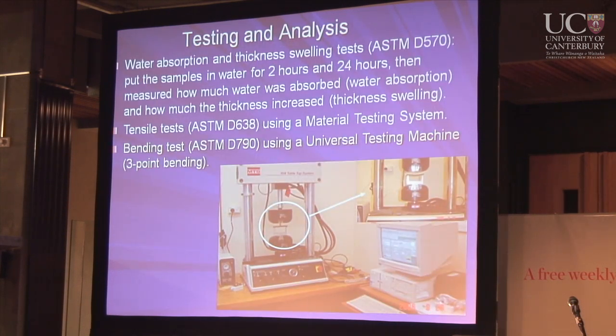Okay, so we do the tests. As I mentioned, we need to look at the stability. We put the materials in the water for 2 hours and 24 hours to see how much water is absorbed by the materials and what the dimensional changes are. And then we do tests for the mechanical properties. We do the tensile test and the bending test to get the stiffness and the strength of the materials.